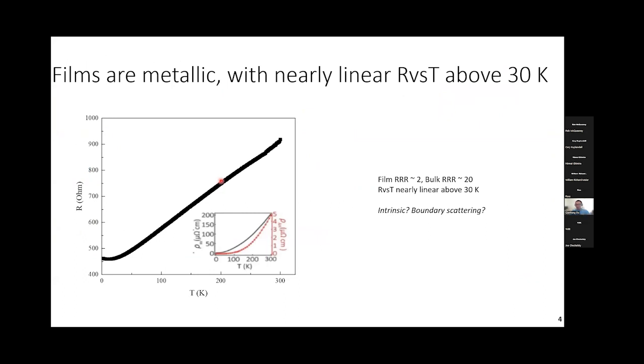When comparing with the single crystal, the film shows similar metallic behavior. But one thing different from the single crystal is that above 30 Kelvin, the R versus T shows a nearly linear behavior. And when comparing with the single crystal, we have about one order smaller RRR, which we think comes from the island structure of the film.